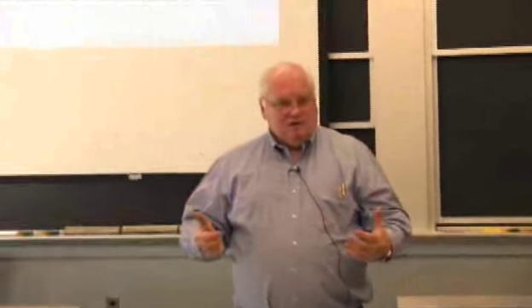So I used to think when I was a bachelor student here, and I was doing wire drawing for my thesis to make superconducting wires, that I would do better if I had a great big set of wire dies. You could buy diamond dies for 20 bucks a piece back then, so I had a government research contract. I went out and bought $1,000 worth of dies, and I had them in 5% increments. Well, that was the wrong way to go. You really should be doing 30 or 40 or 50% draws and not 5 or 10% draws. Because with 5 or 10% draws, you get lousy deltas. You get a high delta operation and you're liable to crack the center. You also are going to get very inhomogeneous deformation when you do high delta. This is the highest delta operation among these four.